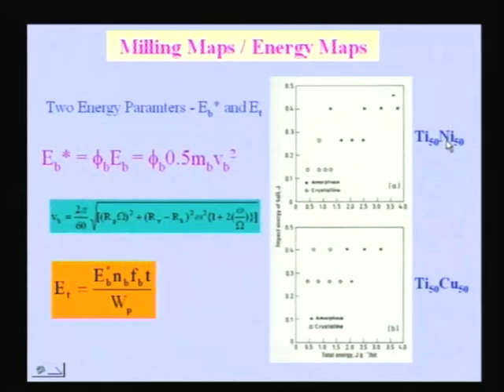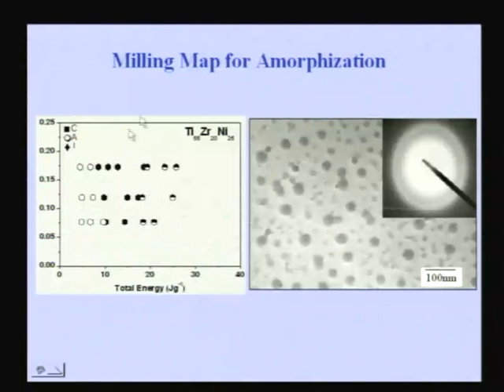You can see this is titanium nickel, this is titanium copper. So if you put a vertical line like this, below that line all are white circles, that means they are crystalline, they have not yet formed amorphous, and beyond that line you have amorphous phase formation. That means there is a critical energy beyond which they form. So the actual impact energy of the ball is not crucial. What is the total energy transferred to the powder over a period of time, that is crucial for any phase formation. And one can do this for various glasses.